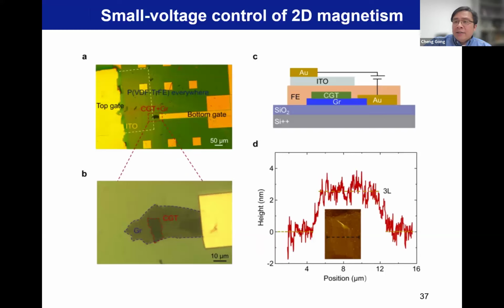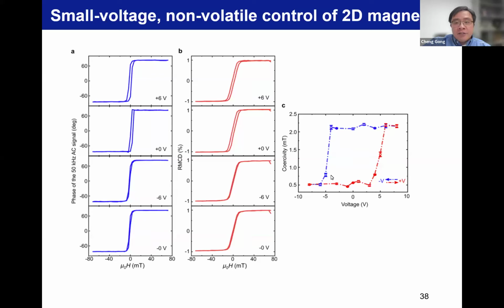So we remodified the device. As you can see in figure C, we now use a bottom graphene electrode. And between the bottom graphene electrode and the top ITO electrode, you have the heterostructure. And then you are not wasting voltage across silicon oxide if you apply the voltage through the bottom electrode, silicon. So anyhow, now you can really just use a small voltage to flip the ferroelectric polarization and see the magnetic property change. As you can see, we can use just 5 volts to flip the ferroelectric polarization and see the non-volatile control of the hysteresis loop.